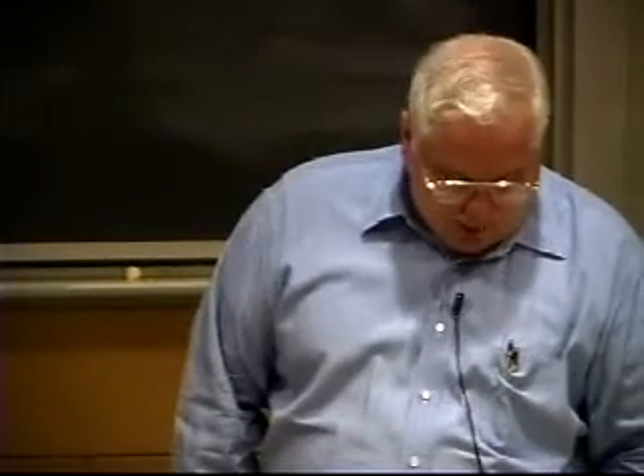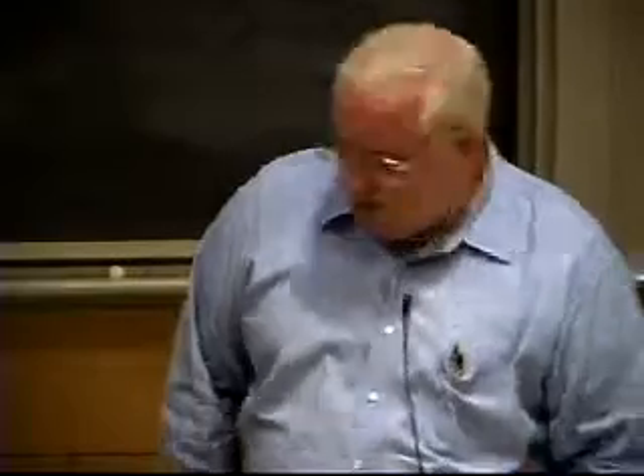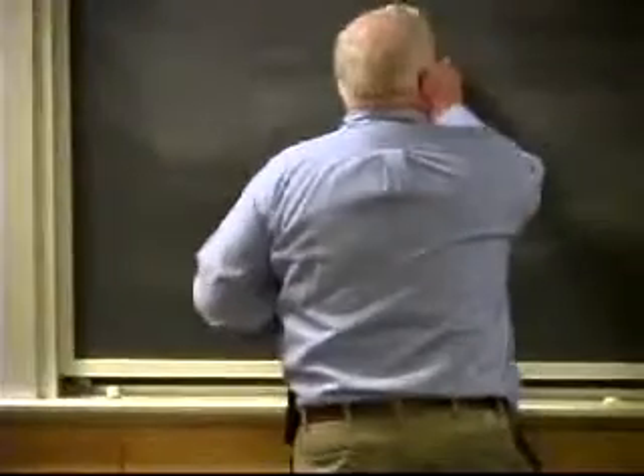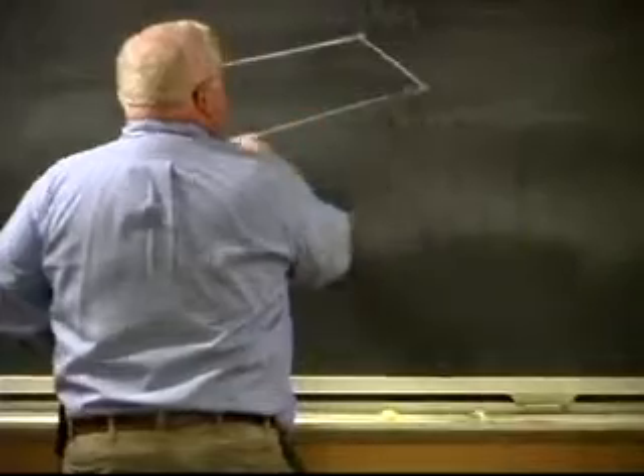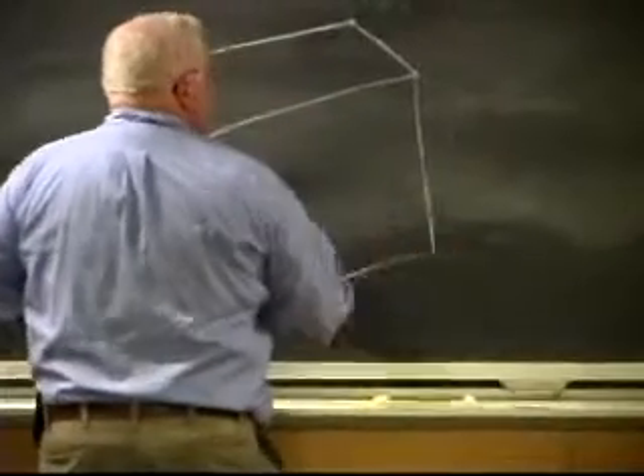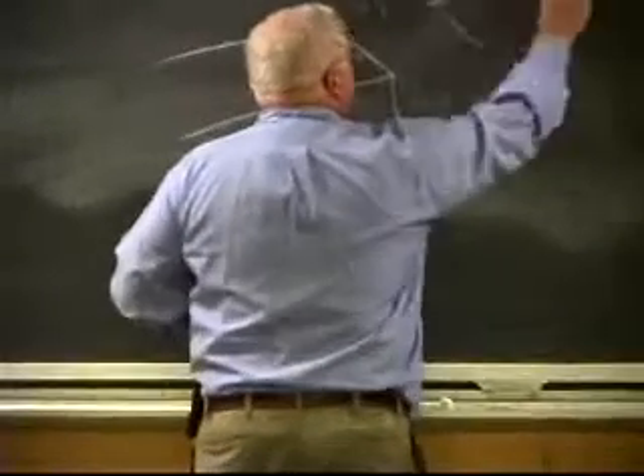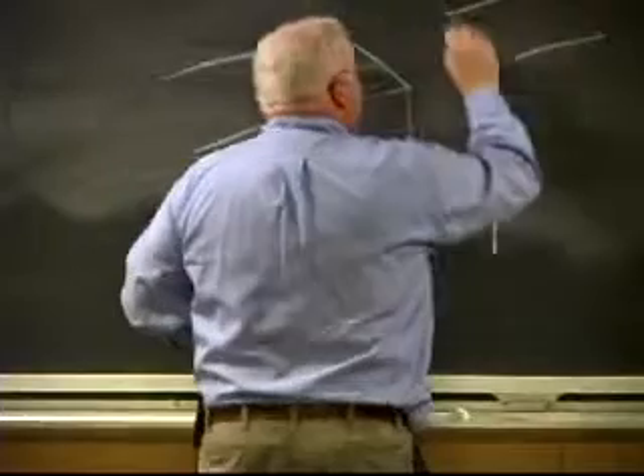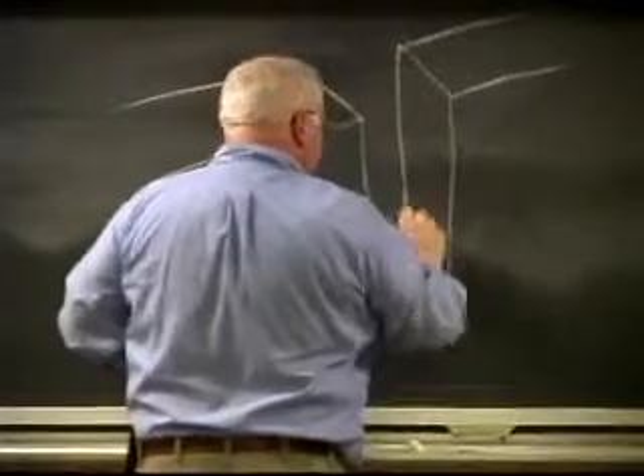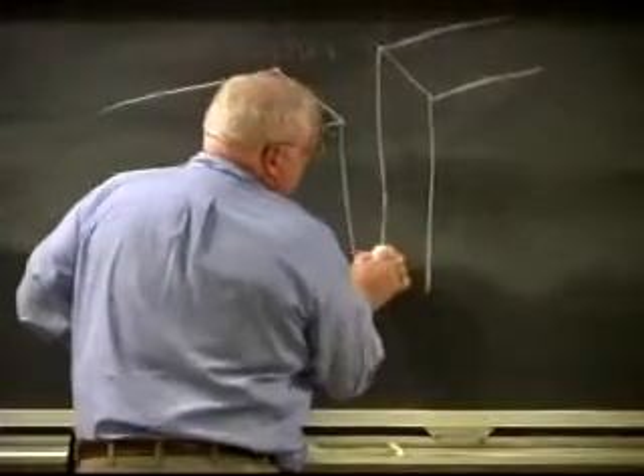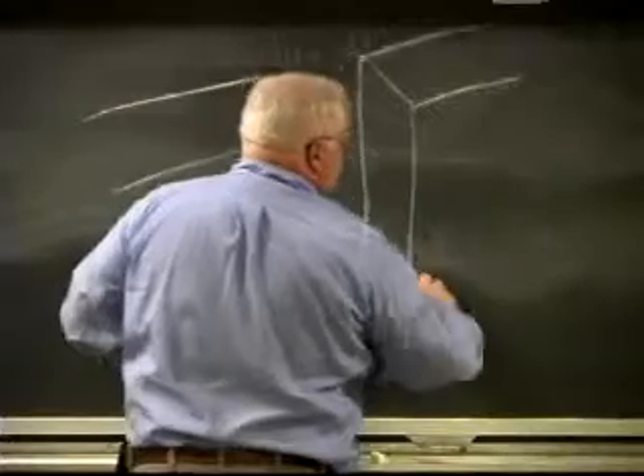Okay, we were talking about submerged arc and gas metal arc and gas tungsten arc welding of titanium. I was starting to talk about electroslag welding of titanium. We actually do a lot of electroslag welding of steel. Electroslag is a process for vertically welding heavy plates. I'm trying to do a three-dimensional perspective here.